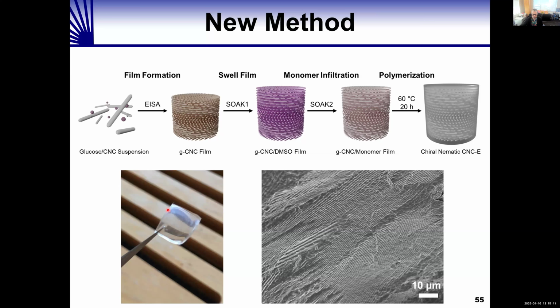And if you take a cross section of this film and look at it under an electron microscope, then you can again see the well-ordered layered structure that emerges from the chiral nematic organization of the cellulose nanocrystals.